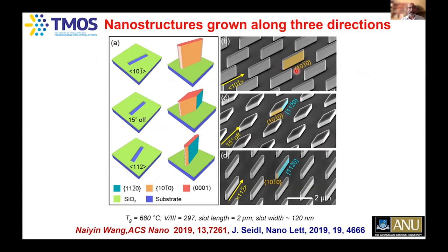If you open the slot along another crystallographic orientation, you also create membranes, but these membranes are thicker than these ones, and they also have a different facet. But if you open the slot in between those crystallographic orientations, suddenly you start creating these nanodiamonds, and you can have these side facets alternating between these two. So now you can see, instead of just making nanowires, we're able to make thin nanomembranes, thick nanomembranes, nanodiamonds. It really opens up opportunities for us to make a wide variety of nanostructures.